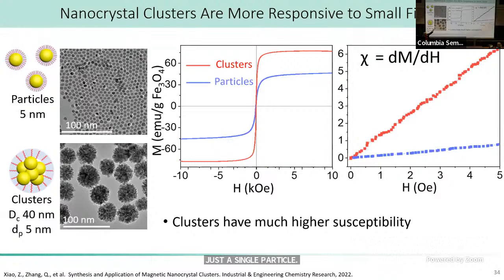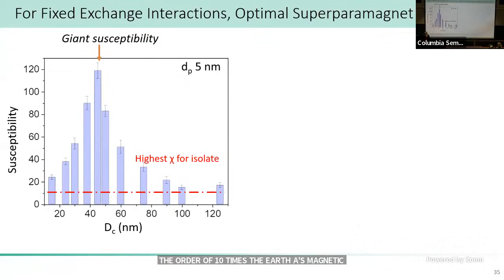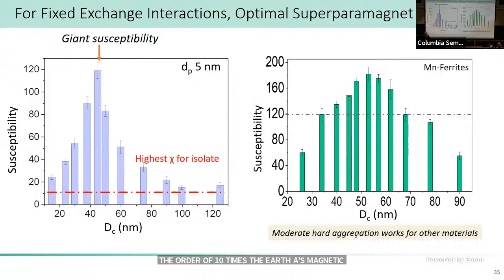So this is a comparison of clusters and particles. These are field strengths that I'm showing here, which really are on the order of like 10 times the Earth's magnetic field. So very, very low field strengths. On the right is actually the data, and on the left is kind of a different view of the data. One is a ferrite and one is an iron oxide. We'll talk about this one. We're able to get very, very high susceptibilities, and this is in a solid phase. In a liquid phase, they can be an order of magnitude higher.